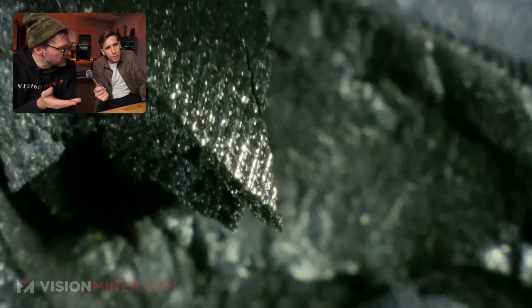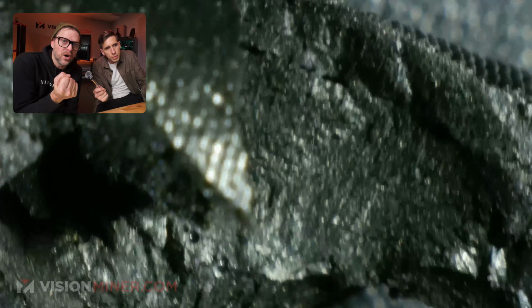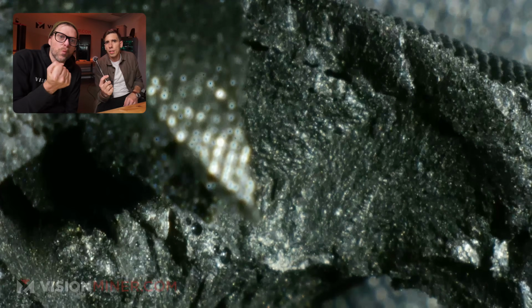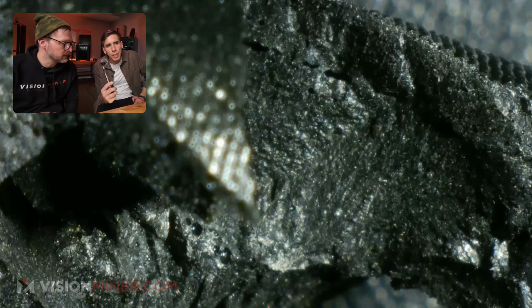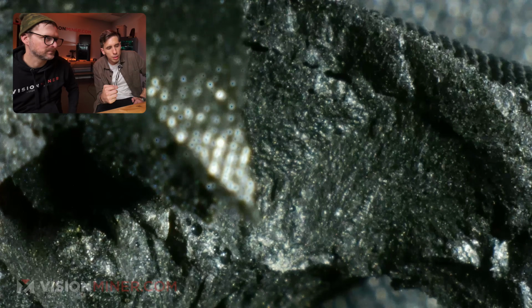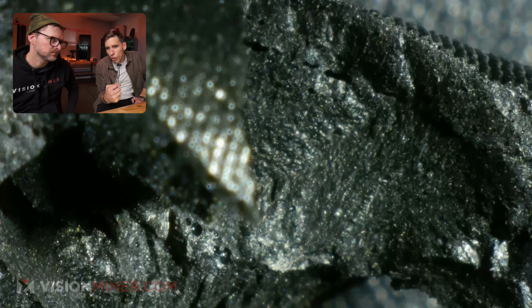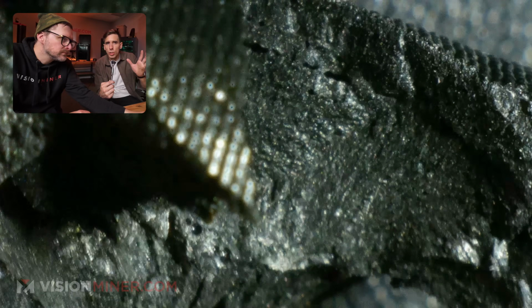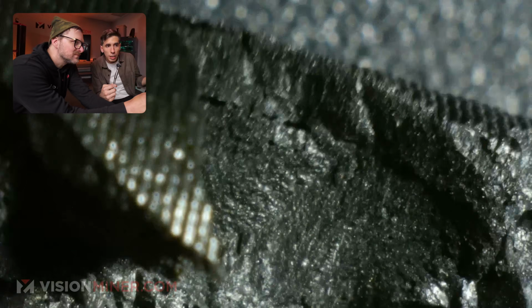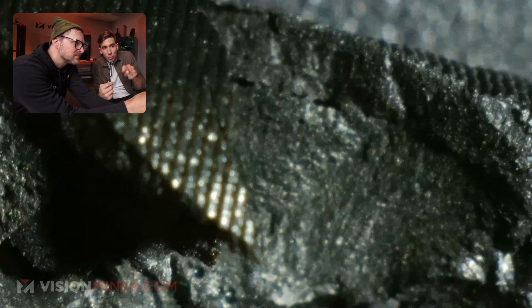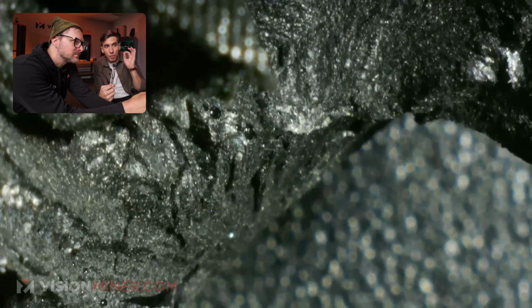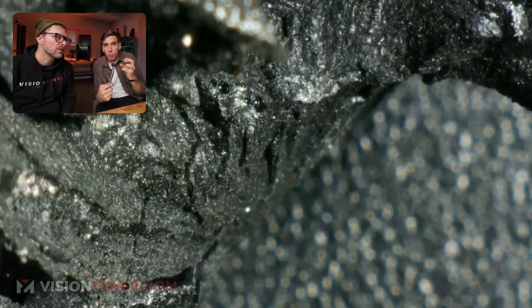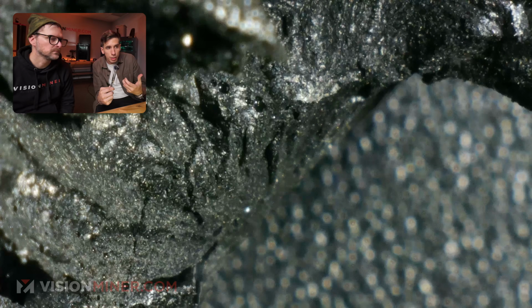I guess you'd call it isometric, but you're not seeing it break along a specific layer line. There's no one weak point in this print. Yeah, isotropic. So in FDM 3D printing, everybody knows, oh yeah, but your Z adhesion is going to be worse and it's going to be weak along the layer lines. But when we see breaks like this, it's indicative of very, very good layer welding, layer bonding, layer adhesion, generating basically isotropic-like strength. Isotropic being strong in every direction, the same strength in every direction.